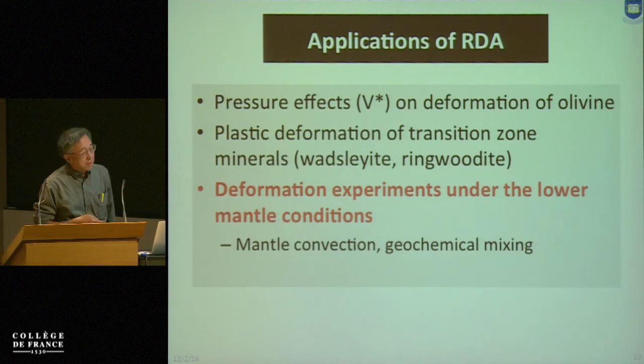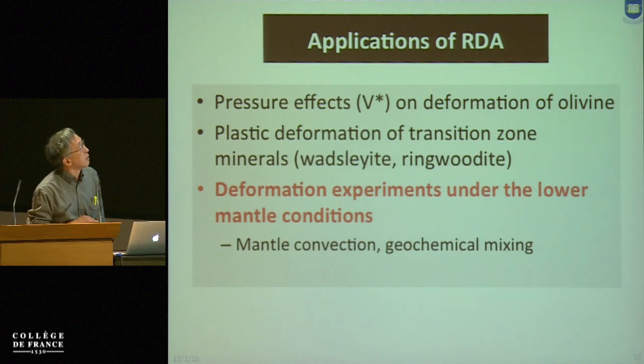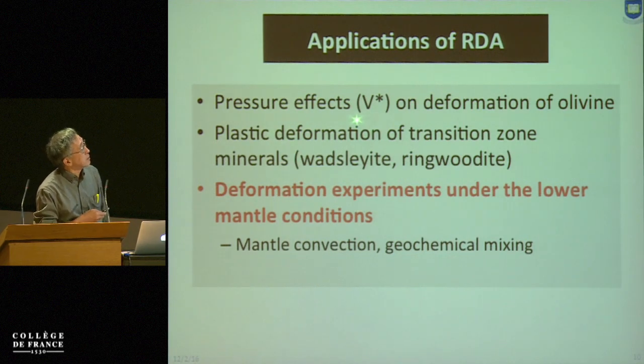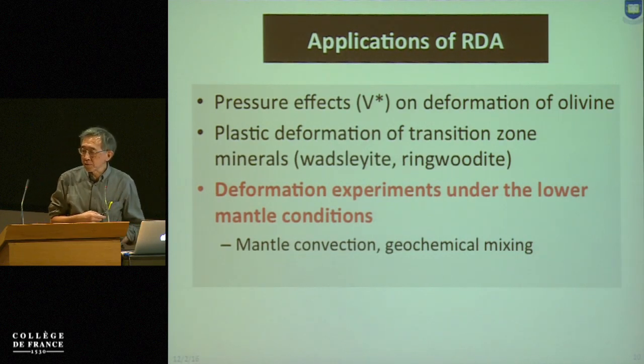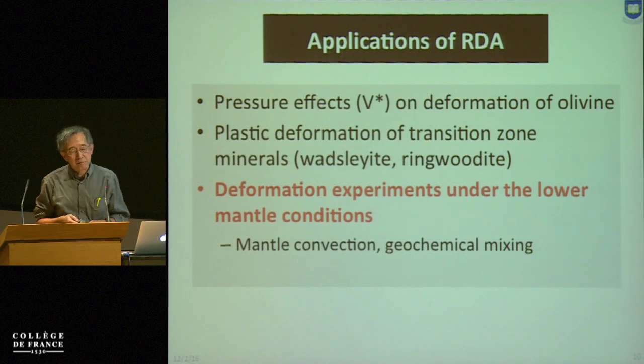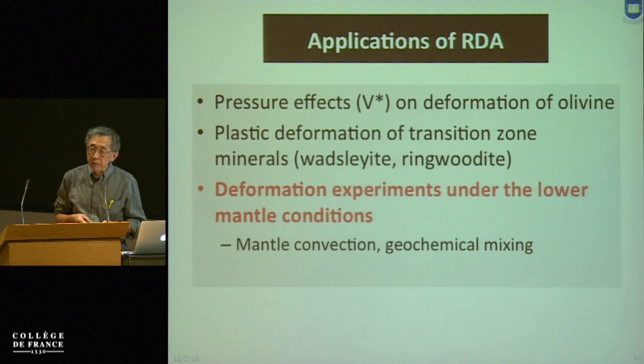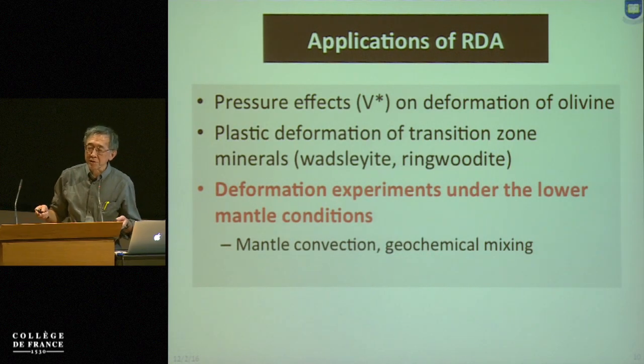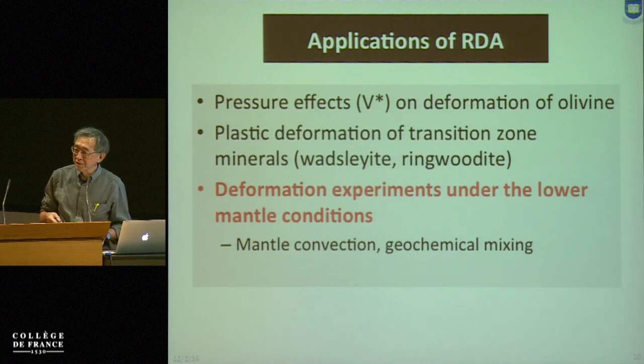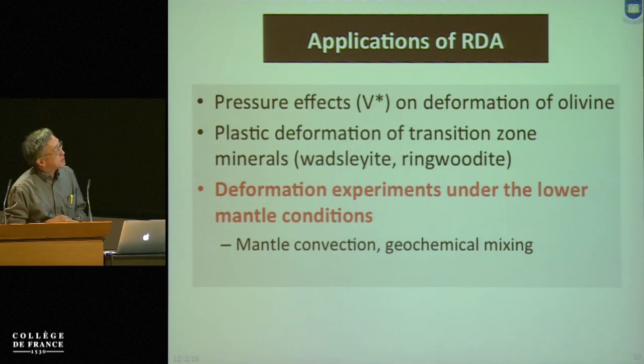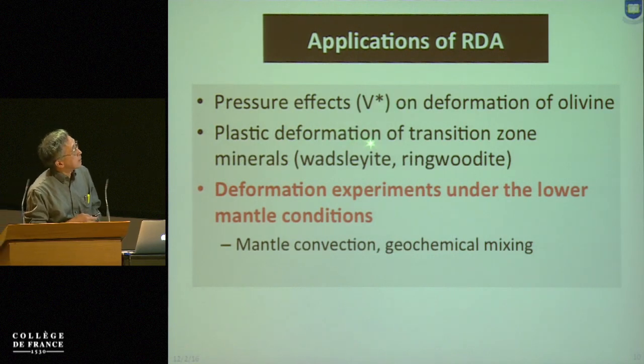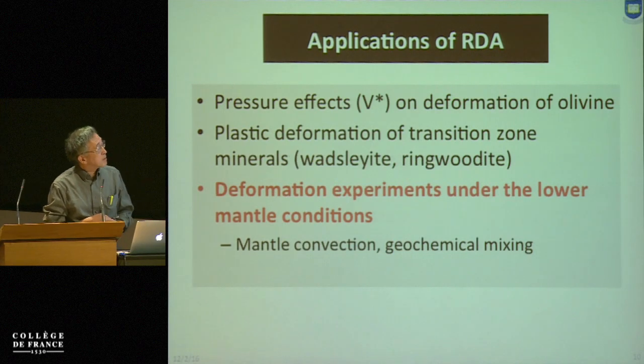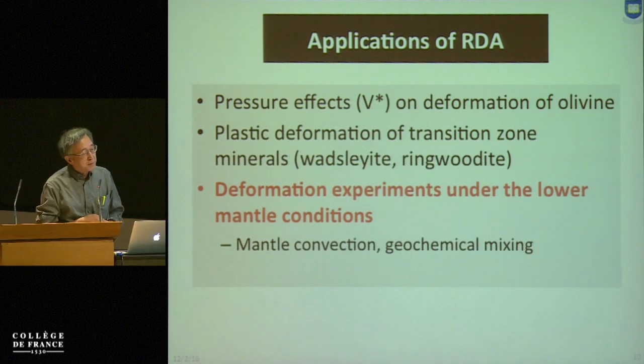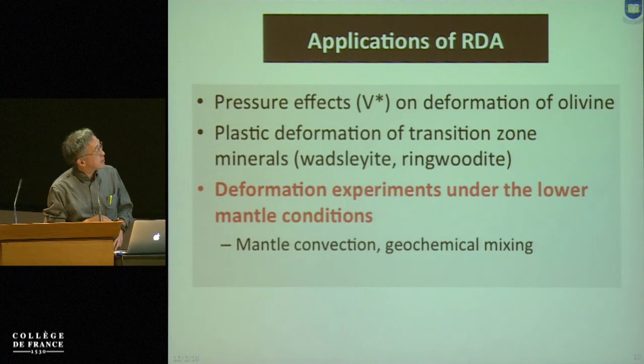We have applied the RDA, rotational Drickamer apparatus, to determine various rheological properties. First, we determined the pressure effects on deformation of olivine, because this was a very controversial issue. Ten years ago, reported activation volumes ranged from 0 to 40, and 0 to 40 makes a huge difference in the viscosity at the bottom of the upper mantle, by something like 20 orders of magnitude. So we determined the activation volume. Then we conducted deformation experiments on some of the transition zone minerals, wadsleyite and ringwoodite, and finally we did experiments at lower mantle conditions.